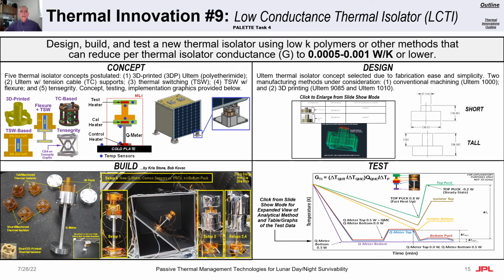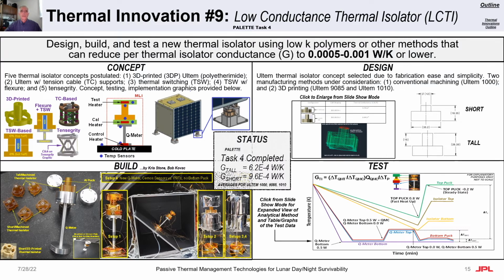Thermal Innovation 9 is the low-conductance thermal isolator. 3 material types were tested, machinable Ultem 1000 and 3D printable Ultem 9085 and 1010 in 2 sizes, short and tall, which indicated superior thermal isolation performance consistent with thermal predictions.